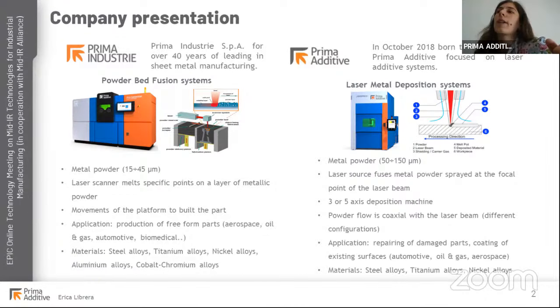And the laser is coaxial with the powder flow, focused on the same point as the powder. The powder also has a focal point, with a circular geometry. The movement of the heads and the nozzle tips allows the generation of three-dimensional geometries. This kind of approach is particularly indicated for repairing applications, recoating and repairing or remelting of pre-existing surfaces. The powder bed instead is optimal for the generation of free structures for the aeronautical sector, for the biomedical sector, many